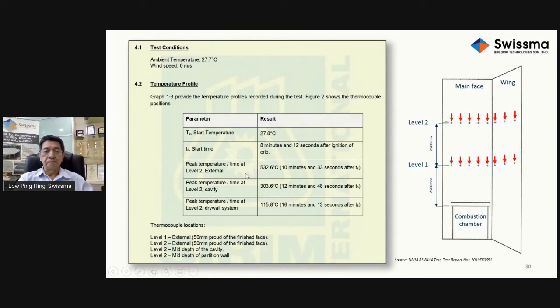The peak temperature measured at level 2, which is here, was 532.6 degrees Celsius. And it reached that temperature after 10 minutes and 33 seconds. That means if you add these two together, from when you start the fire it's 18 minutes, 45 seconds before this temperature is reached. But when you start your timing from start time, it is 10 minutes, 33 seconds.